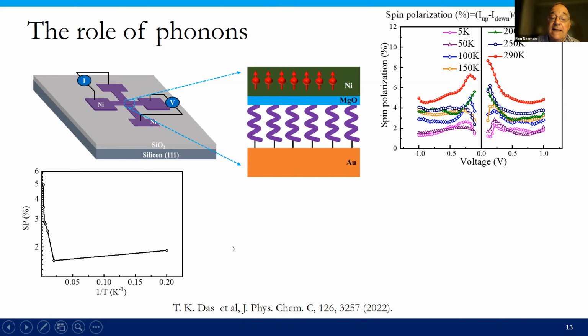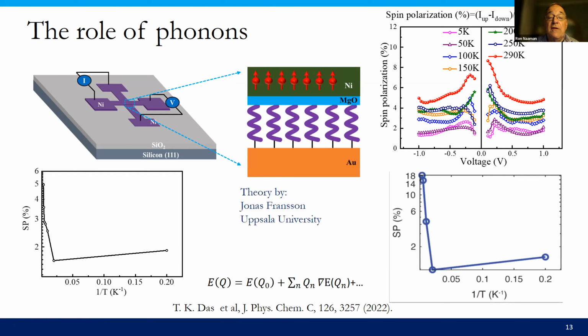So how can we understand it? We did this in collaboration with Jonas Fransson from Uppsala University. He derived a theory for it, and basically it comes from the vibronic coupling of the electron with low frequency chiral vibrations. How low frequency? We speak here about 50 wave numbers, about. So it's really low vibrational frequencies. And as you see, the theory follows the experimental results very nicely with very few assumptions. So we think we understand what's going on here. There is coupling of the electron with the low frequency vibration.